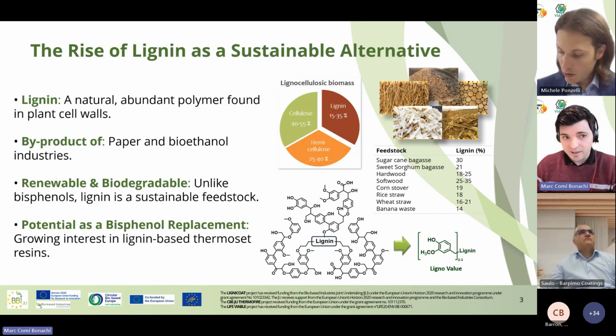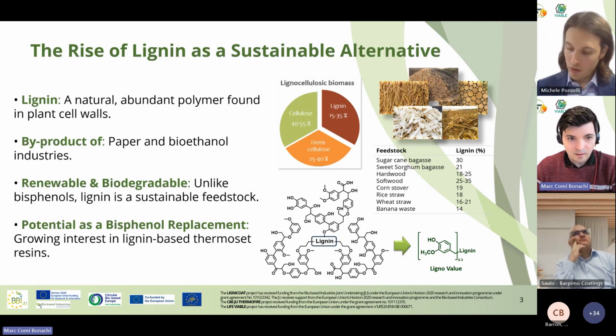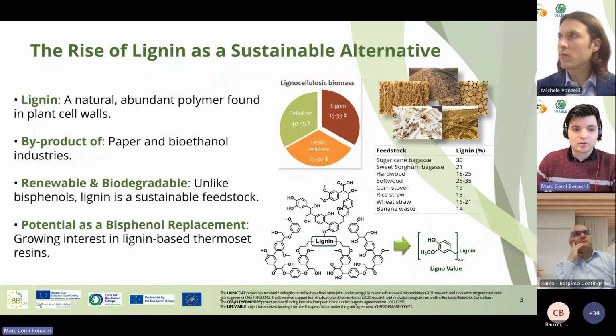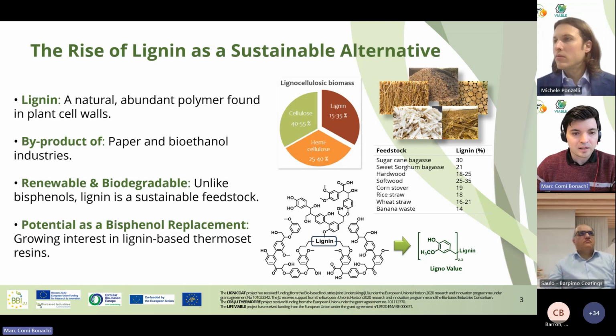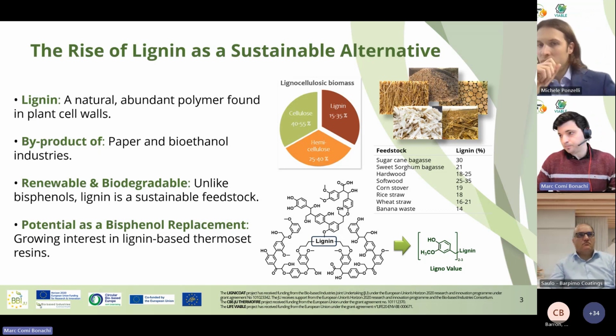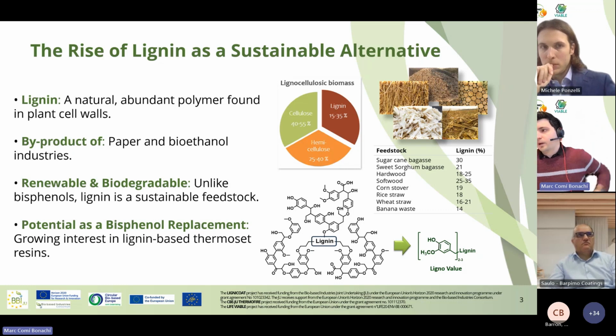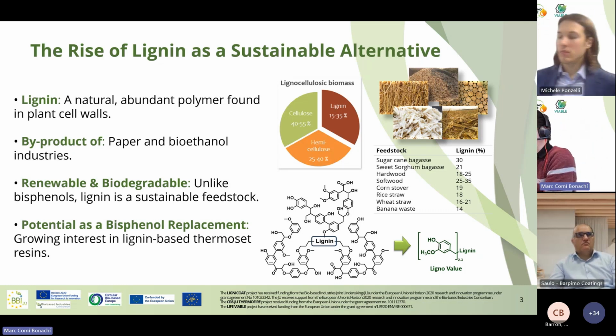bioethanol. Also, lignin is a renewable and biodegradable compound, since it's coming from vegetables, it is renewable, and biodegradable because there are literally some fungi and some bacteria that can degrade the lignin. And as I told you, it is a potential substitute of bisphenol because it shares part of the structure. It's not as defined as the traditional fossil-based bisphenol, but it shares partially the chemical structure. So in different vegetables, we have different content of lignin, as I put you here in this table on the right. And we are going to select for LIFE VIABLE 4 out of all of these different botanical origins and